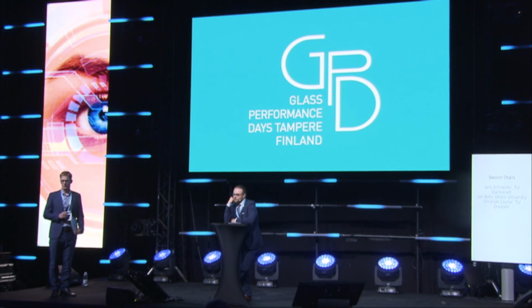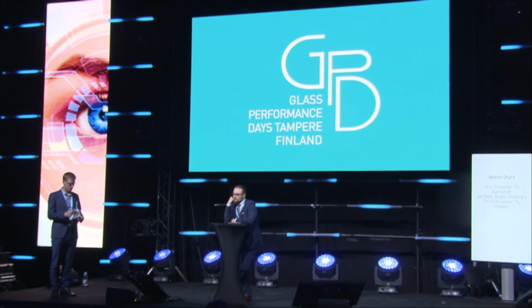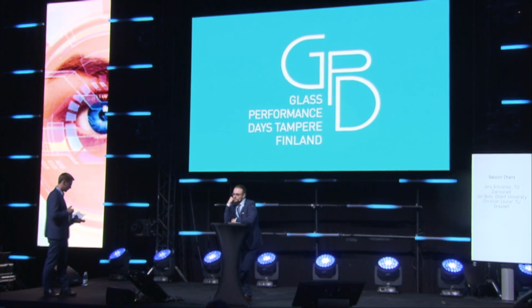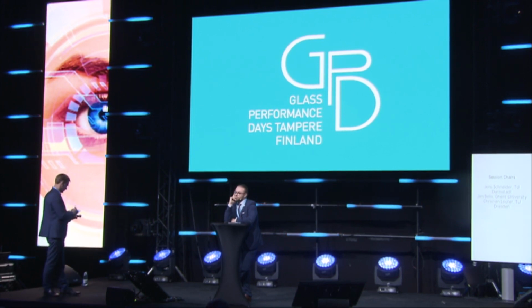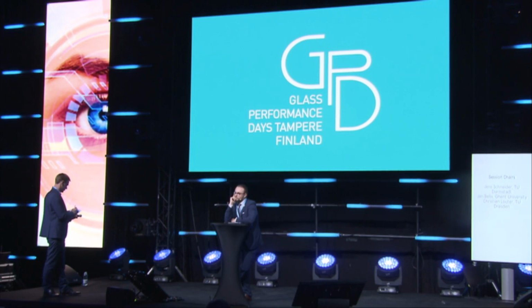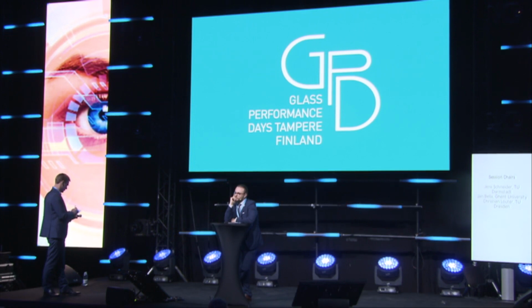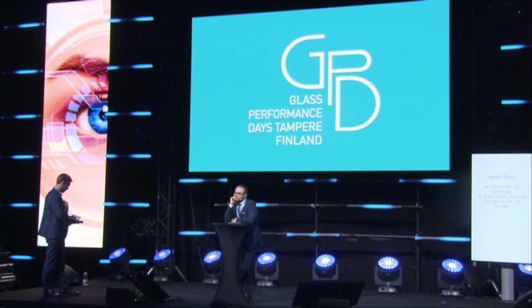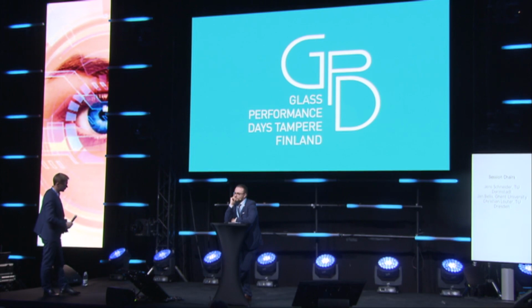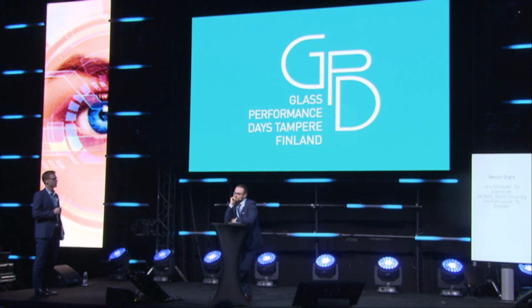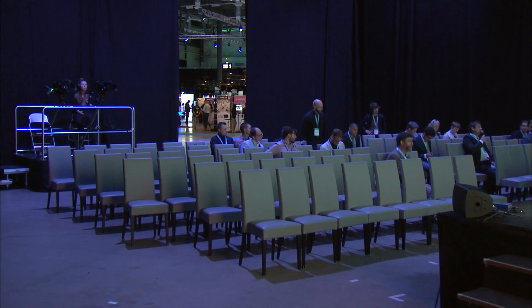You can have cavitation in rubber with no damage, actually, because you just open a bubble and then you unload and the bubble disappears. And so I don't really understand why you use this derivation of what you call a phenomenological model instead of classical models in nonlinear elasticity. Of course, you cannot find it in Abaqus, but there is a huge literature on nonlinear elasticity.